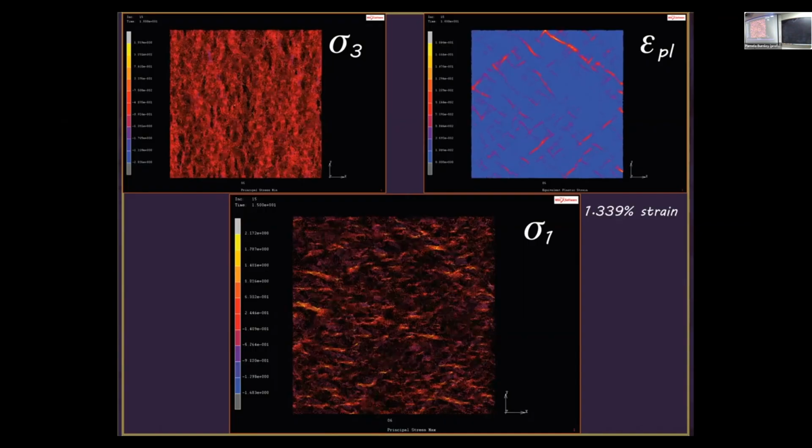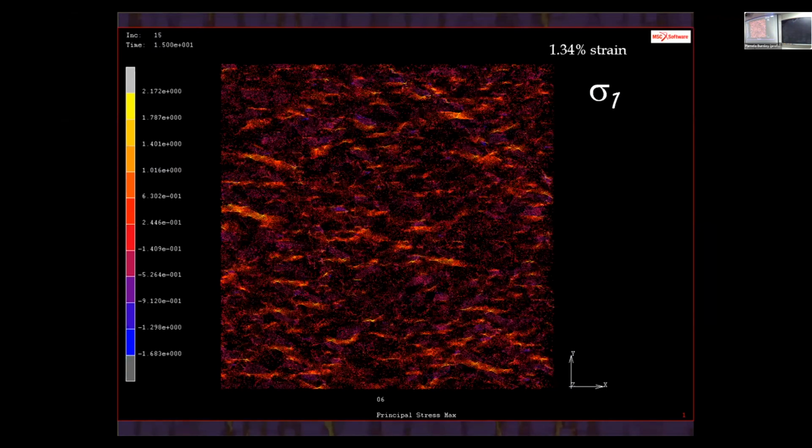All right, so now I want to look at this. I'm going to focus in on the tensile component. Okay, so here's my tensile component. Then what I'm going to do is blank out quartz and the mica, the things with the lower yield strength, so that the feldspars have a higher moduli. If I get rid of them, and you focus on the really bright spots, you can see that those tend to show up more in the feldspar part, okay?